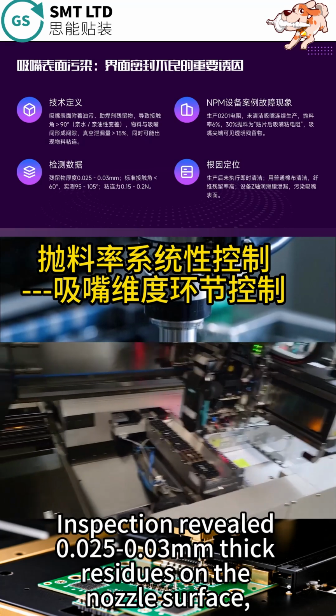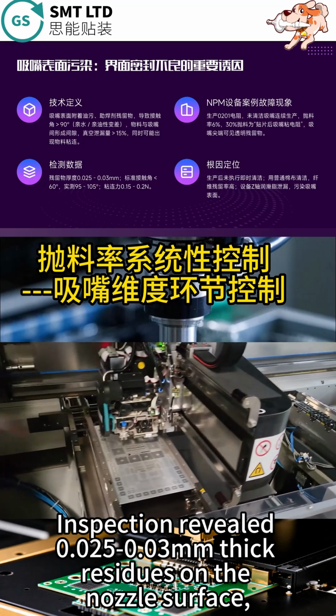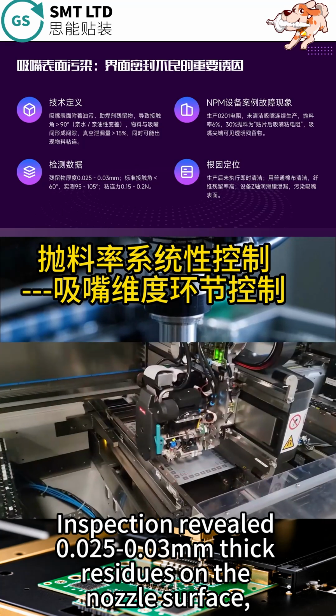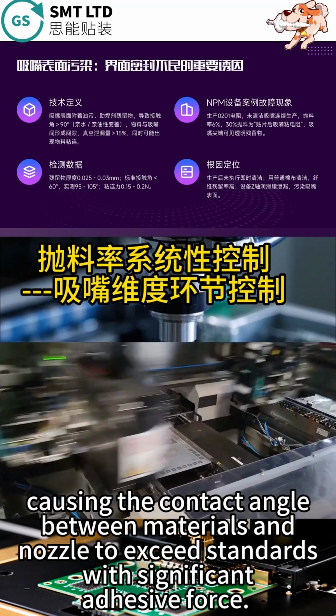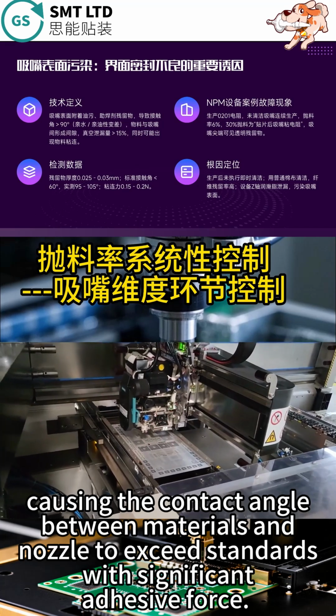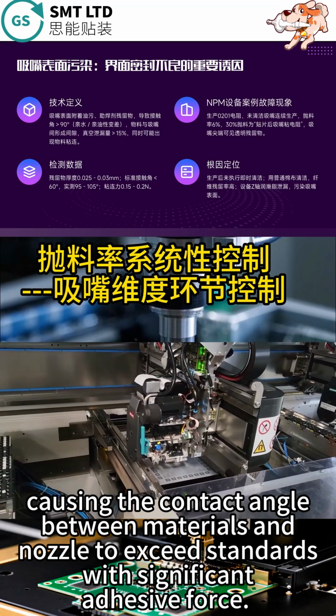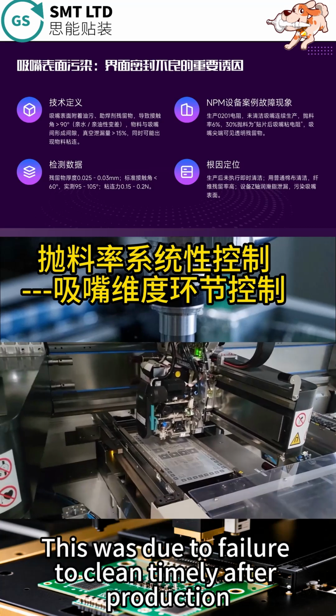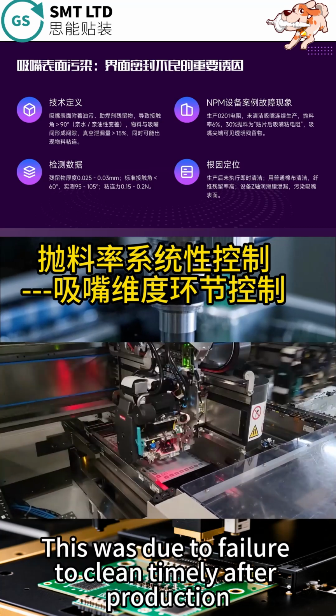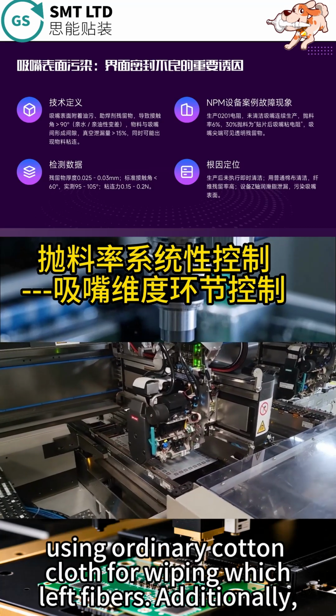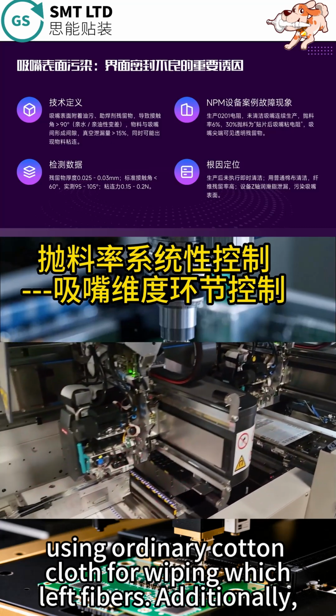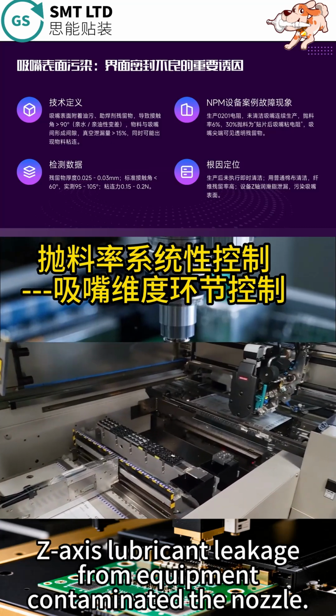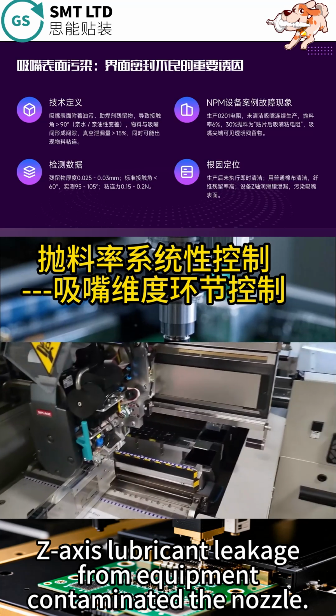Inspection revealed 0.025 to 0.03 mm thick residues on the nozzle surface, causing the contact angle between materials and nozzle to exceed standards with significant adhesive force. This was due to failure to clean in time after production, using ordinary cotton cloth for wiping, which left fibers additionally. Z-axis lubricant leakage from equipment contaminated the nozzle.